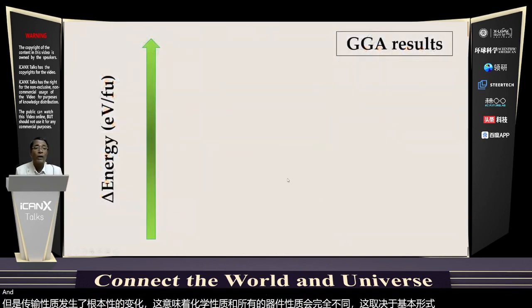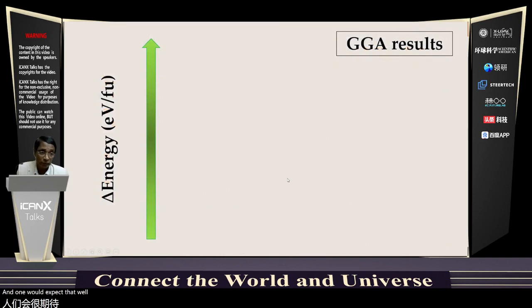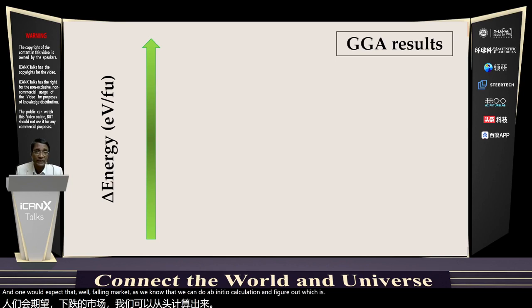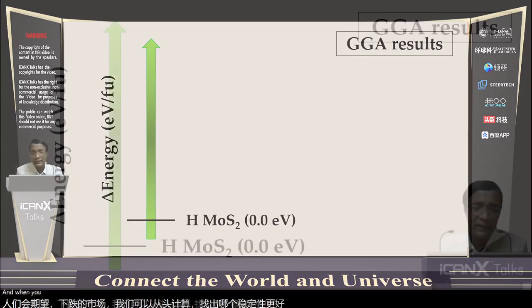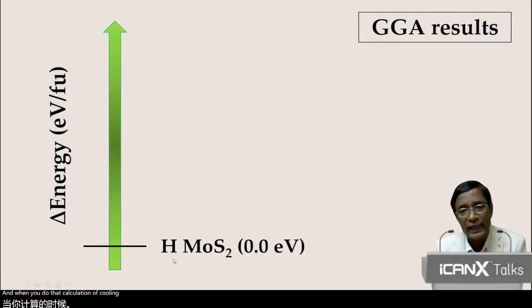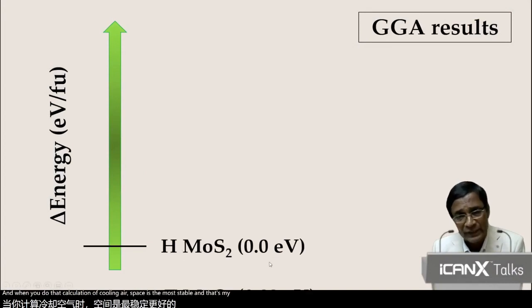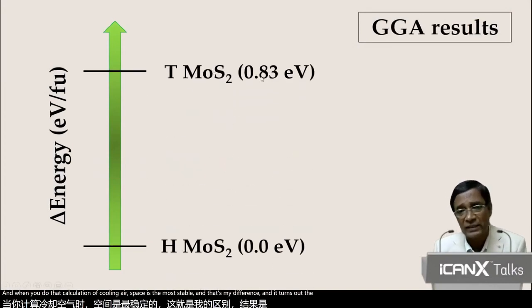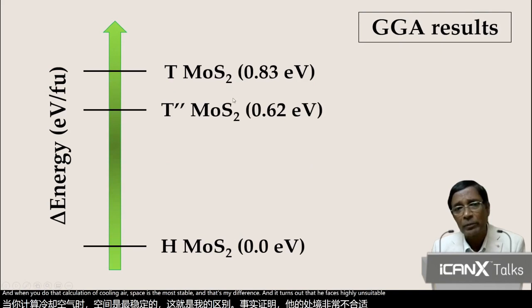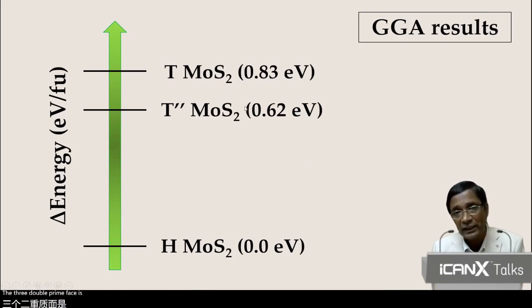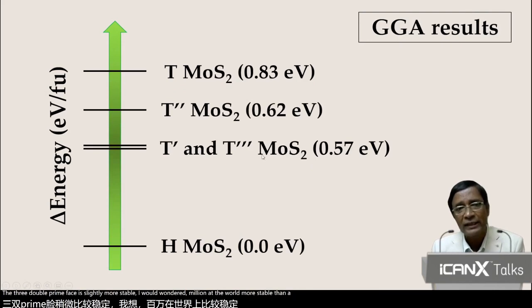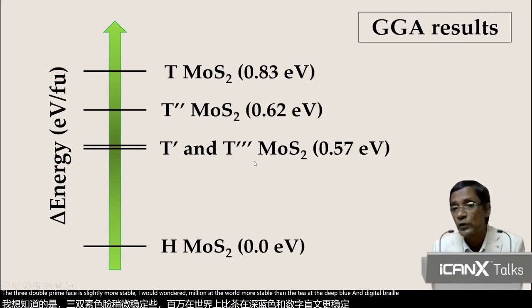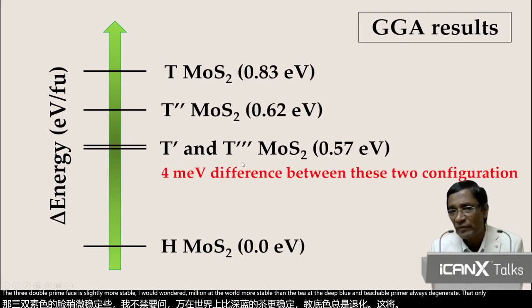And one would expect that, well, following Matthias, we know that we can do ab initio calculation and figure out which has better stability. And when you do that calculation, of course, the H phase is the most stable, and that's my reference. And it turns out the T phase is highly unstable. The T double prime phase is slightly more stable, about 200 millielectron volt more stable than the T, and the T prime and T triple prime are almost degenerate. They're only 4 meV apart.